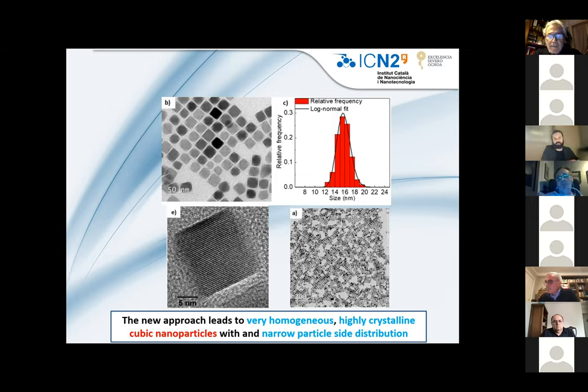Yeah, I think it should be possible. But the issue here is that you have to put some shell, some organic shell or something, to be able to separate them more. This may interfere later with your heating. We have actually tried putting larger organic surfactants on the surface, and that usually has a detrimental effect on the heating, but I don't know how much, because we never did a systematic study. I know people have used silicon oxide shells, grown at different sizes, and seen how it affects the hyperthermia. For larger silicon oxide shells, yes, the hyperthermia gets worse. We just used organic shells, and I don't know how much that would affect the heating. We never tried.